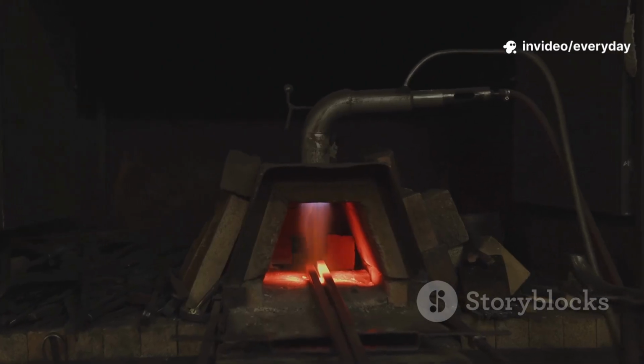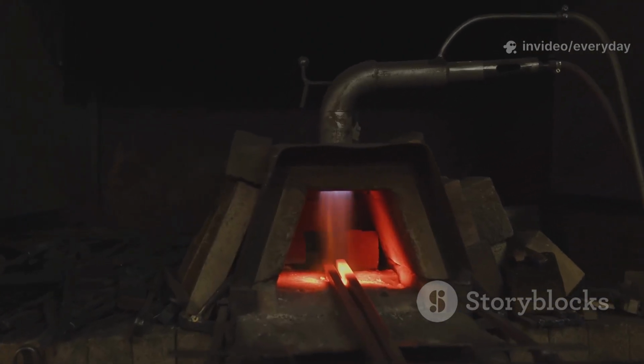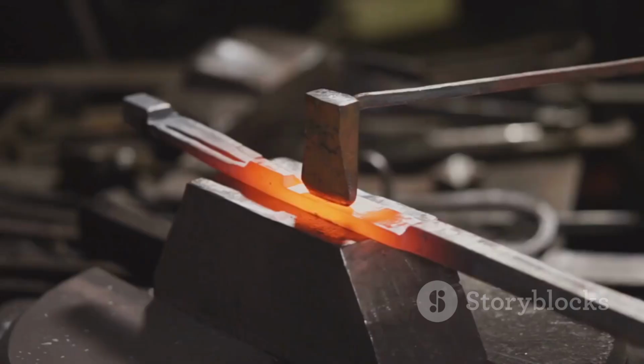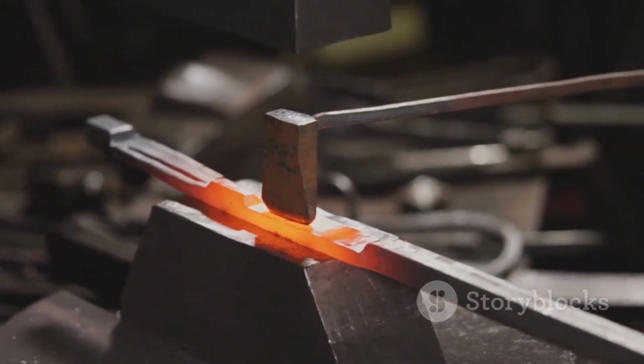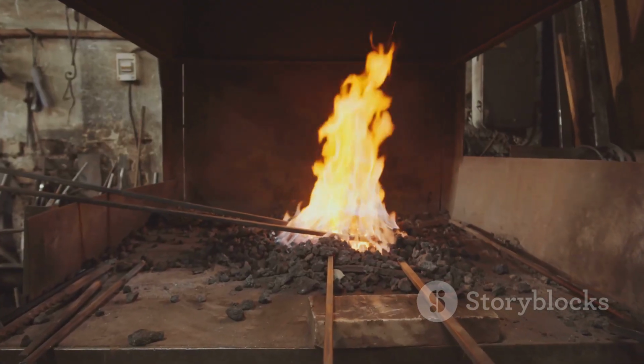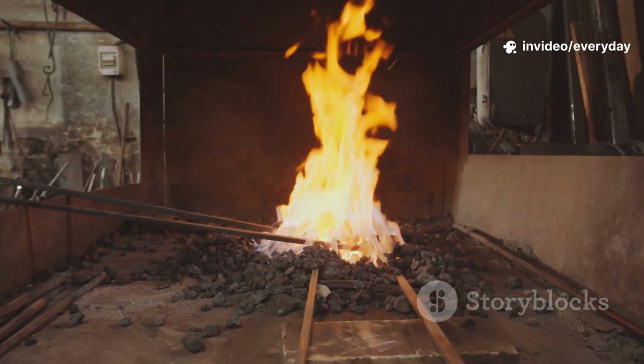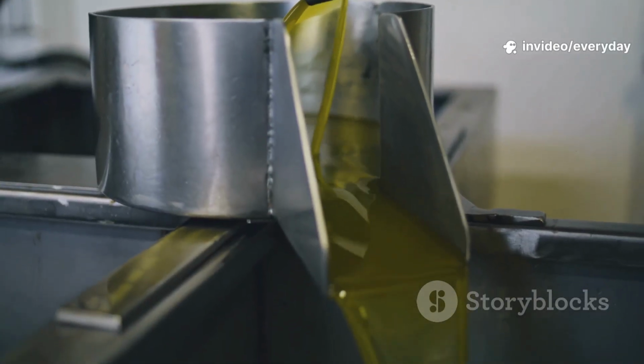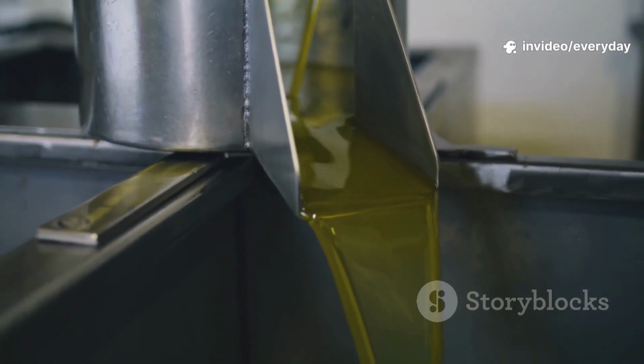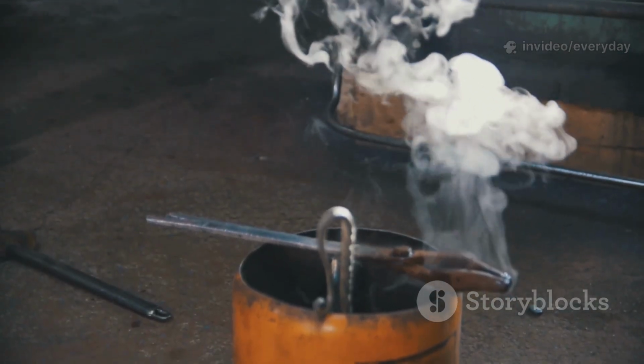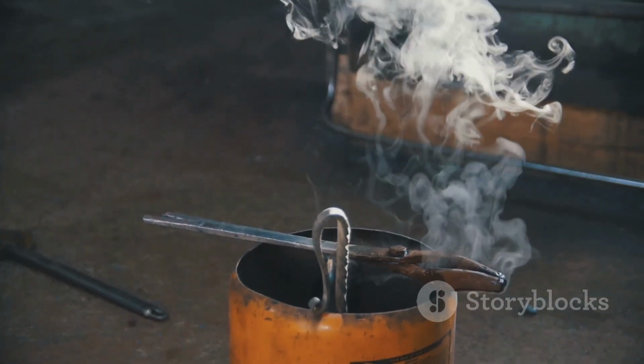For 1095, austenitize around 1475 to 1500 degrees. Non-magnetic at critical is a reliable cue. Heat evenly and give a brief soak. Too long grows grain. Quench in fast to medium oil. Move gently to break the vapor jacket. Water is risky for beginners. Cracks and warps rise sharply.